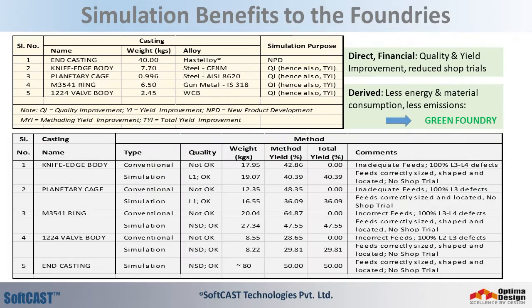These 5 case studies show the considerable benefits that accrue to the foundry by using the SoftCAST simulation and methoding system. Overall yield improvement resulted from 2 sources: 1. Method yield increase, and 2. Indirectly through quality improvement, and thus through reduction or elimination of rejects, and reduction in repairs. Overall yield improvement ranged from 30% to 50% across these castings.